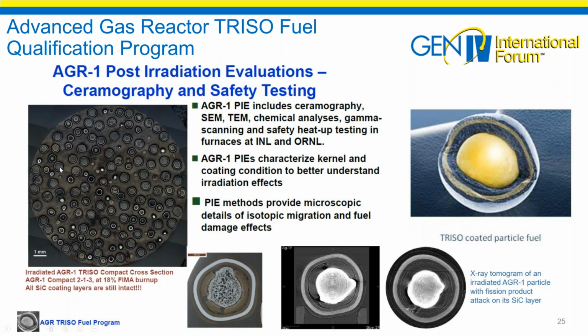And our teams at both labs looked at this and carefully checked as they were polishing the sample, did we have any breaches? And we actually categorized different types of breaches. So, for instance, here the buffer layer cracked and the particle oozed out. But did we have any attack of the silicon carbide layer? Did we breach it? We actually looked for that.